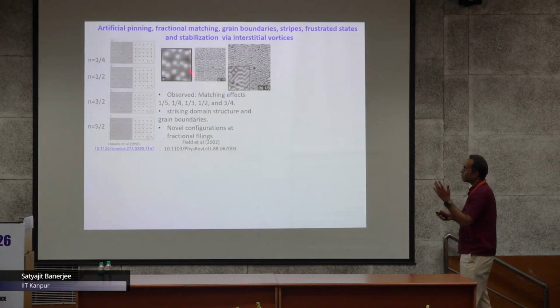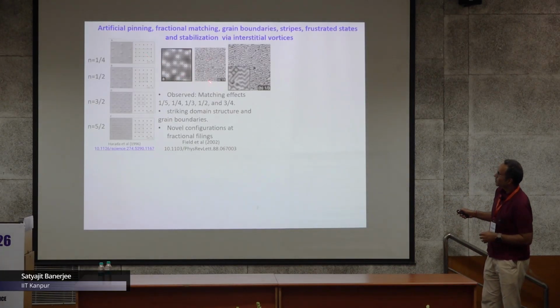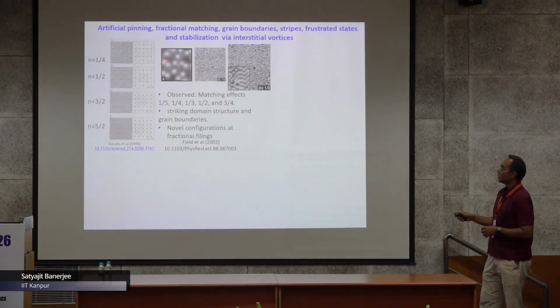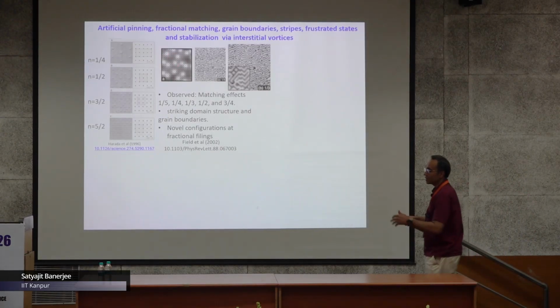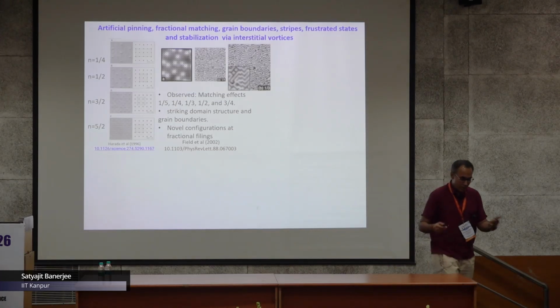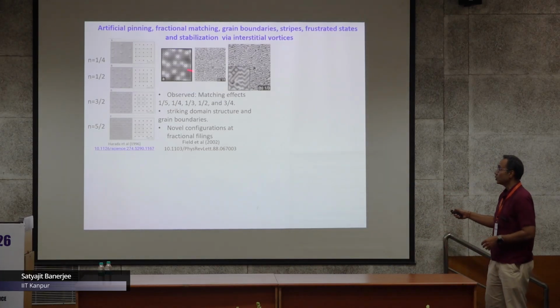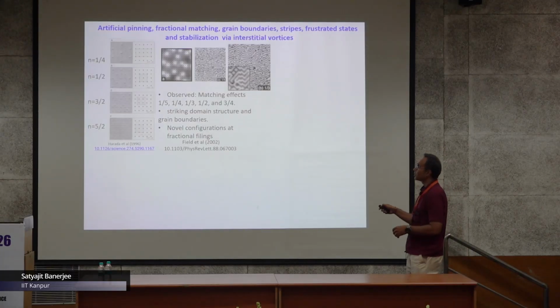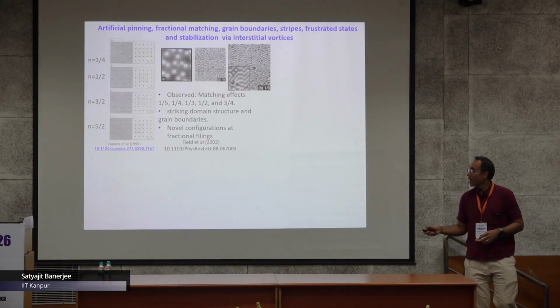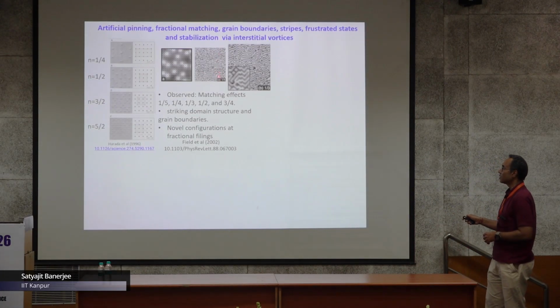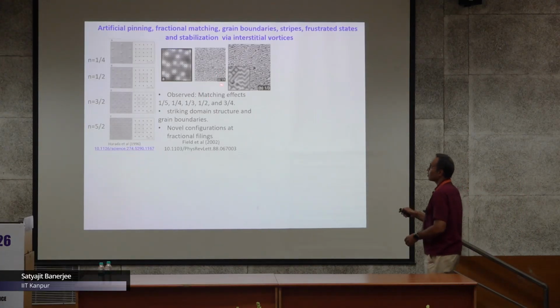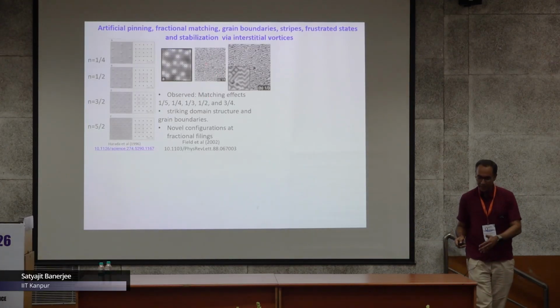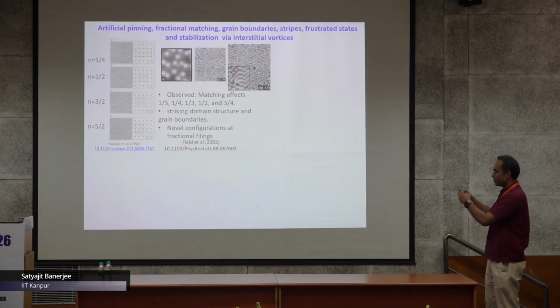Other experiments, though not entirely clear, show a periodic array of holes patterned on a superconductor with vortices, where the number of vortices is much less than the number of holes. These are fractionally filled vortices, fractional filling, not matching the number of holes, yet quite stable. People also found grain boundaries, similar to the soliton-like excitations I mentioned, where stress builds up.